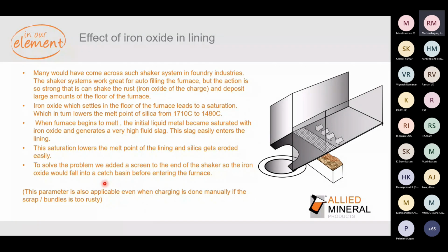And when the lining is new and fresh, it has high chances, because the lining is like a honeycomb, so it tries to suck up the oxides and saturates very fast. So what happens is this saturation lowers the melting point of silica and erodes the lining pretty fast.